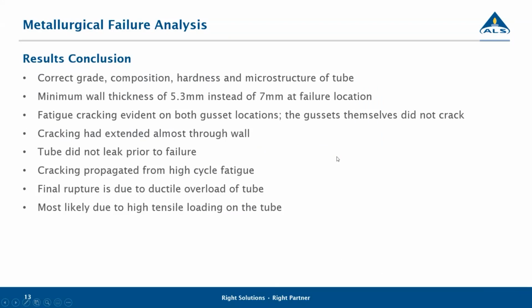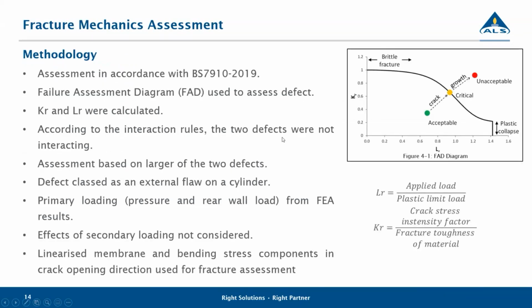So in conclusion, on the metallurgical side, the correct grade and composition, hardness and microstructure of the tube was present. The minimum wall thickness of 5.3 instead of 7 millimeters at the failure location played a big role. Fatigue cracking was evident on both gusset locations. The gussets themselves didn't crack, however. Cracking had extended almost through wall, but the tube didn't leak before failure. And cracking propagated from high cycle fatigue. The final rupture was due to ductile overload of the tube and most likely due to high tensile loading on the tube. So that was a big question. Was there something that happened that overloaded the tube?